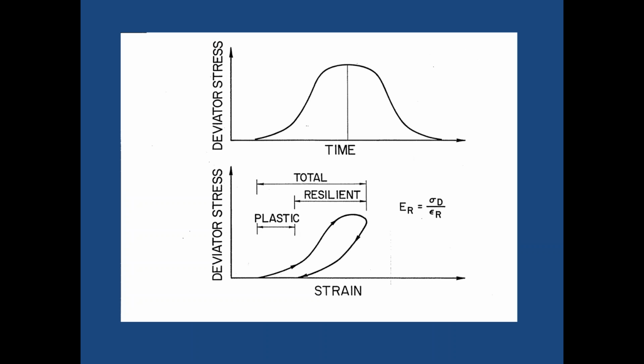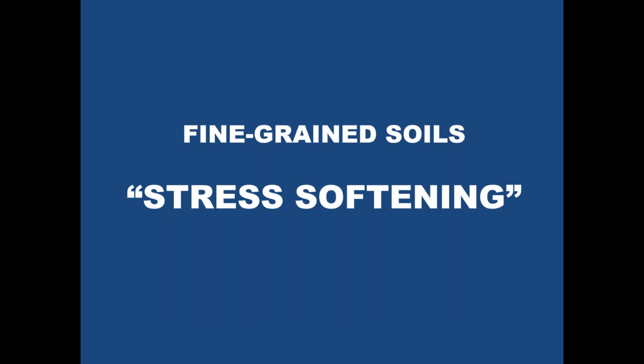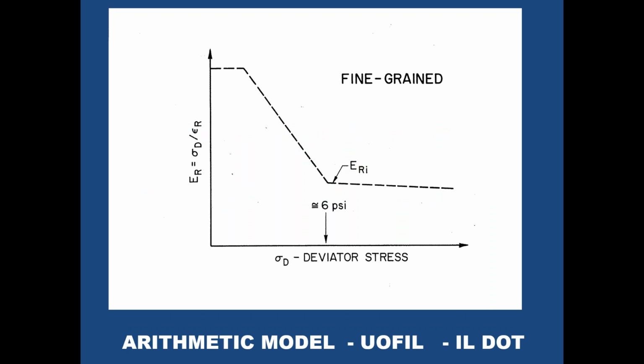If you look at resilient modulus, we have a repeated deviator stress. We measure total strain and recoverable resilient strain. Resilient modulus is the repeated deviator stress divided by the resilient strain. Fine-grained soils are stress softening. The higher the stress state, the lower the modulus. This is a typical one that we developed years ago and used in our work in Illinois for the Illinois DOT, showing the modulus as a function of deviator stress. Interestingly enough, somewhere around 6 psi, you start finding the effect of the stress state drops off considerably. That's not a magic number, but it's a good number.